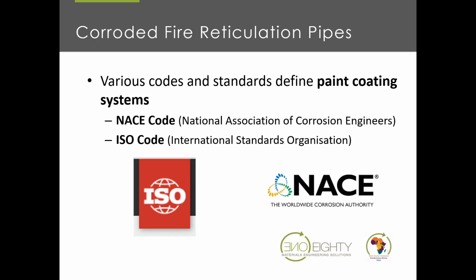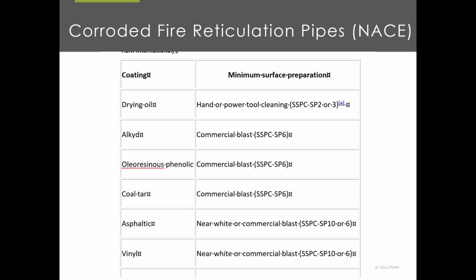In the case of the fire reticulation pipes, an alkyd paint was used. So that red paint that you see on fire reticulation systems is an alkyd paint. It's also the same type of paint they use in structural members inside buildings. It's the correct type of paint. It's the appropriate type of paint for the problem. But it does require what is called a commercial SSPC SP6 sandblasted surface. So that means that the pipes need to be sandblasted with a sandblasting gun before the paint coating is applied. And in fact, the paint coating needs to be applied within 2 hours after sandblasting, because otherwise rust just reforms.